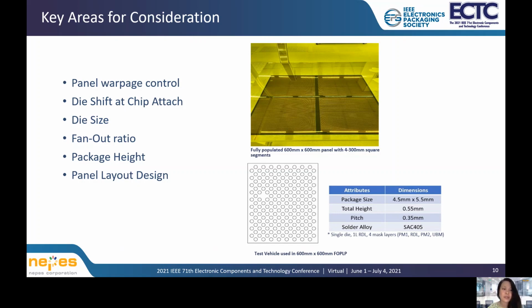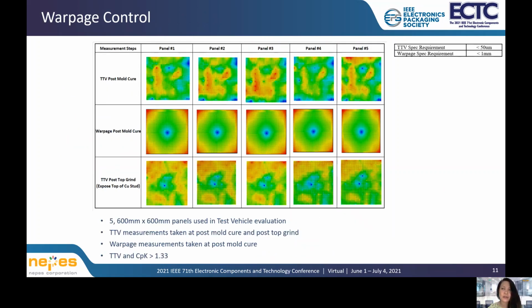Warpage control requirement for the 600 millimeter fan-out PLP is as follows. TTV must be less than 50 microns, and panel warpage must be less than 1 millimeter. In this evaluation, 5 600 by 600 panels were used. TTV measurements were taken at post-mold cure and post-copper stud top grind. Warpage measurements were taken at post-mold cure. Both TTV and CPK measure was more than 1.33.